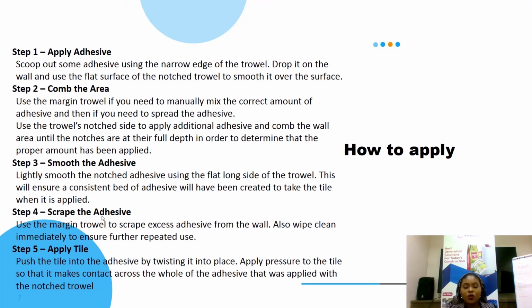So use your notch trowel, spread it evenly, place your tile on the surface, and then you introduce a twisting movement. Twisting, and you press and you place it properly, and you proceed to applying other layers of your tile adhesive. And grouting can take place between 24 to 48 hours after tiling. And if you're using the fast setting adhesive, you can start grouting within 8 to 10 hours. So this is all we have on tile adhesive.